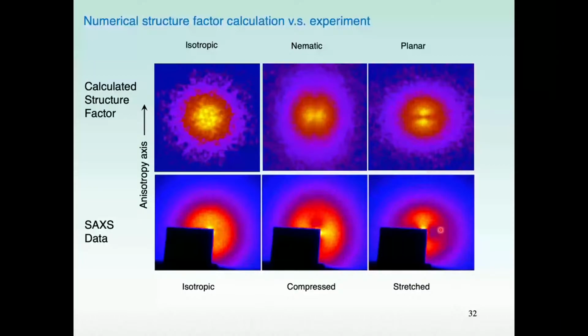And just the opposite for the planar aerogel, the numerical calculation shows, again, this stripe of strong scattering, and this is in the long distance limit. I mean, close to small q, then you're sampling the long length scales aspect of the problem. But also interesting is that at shorter length scales, which is the outer region here, you have just the opposite effect. It's, I think, pretty clearly indicated here in this upper middle calculation of the calculated structure factor. You see this ellipse shape is just the opposite to the long length scale behavior, which is shown for small q to be perpendicular to it. And we believe, although I have not yet published, that this is strongly related to the orbital flop that we've observed in both phases.